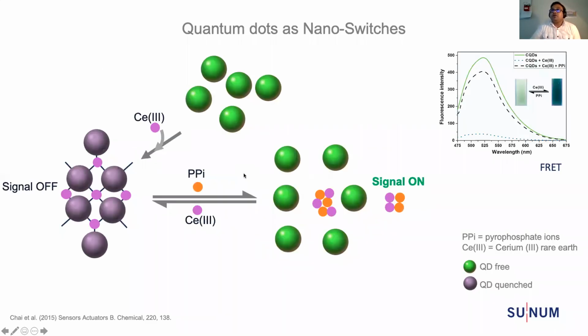How do we use quantum dots as nano-switches? One of the best ways, the simplest way, is shown in this slide. When you have these nanocrystals homogeneously suspended in a colloidal fashion, they don't settle down. They collide with each other and bump into the solution and remain colloidal all the way, no matter how long you keep them. But the problem is, if they are not surface functionalized, they tend to aggregate and settle down, and you can see it with your naked eyes.